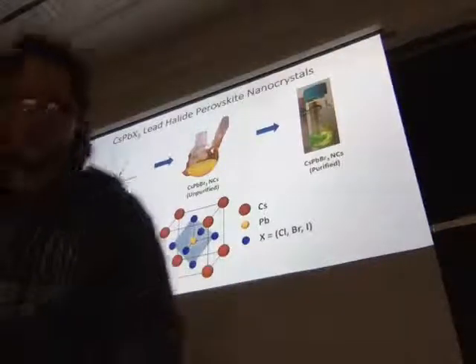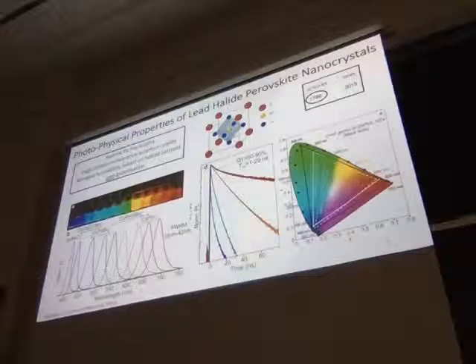The first paper to publish about these came out in 2015, they're the first ones to make nanocrystals out of these materials. They found that these materials are very versatile because they have very narrow PL line widths and a high quantum yield, and you can tune the emission spectrum of these materials by changing halide content and quantization. This figure is from the original paper on these materials. You can make colloidal solutions spanning all the way from 400 to 700 nanometers. And this shows the line widths and all the possible color schemes you can make.